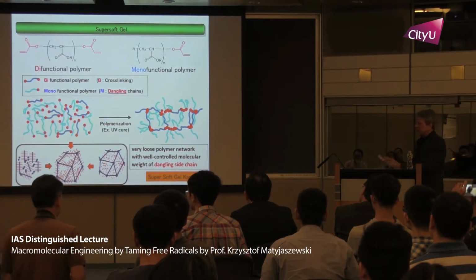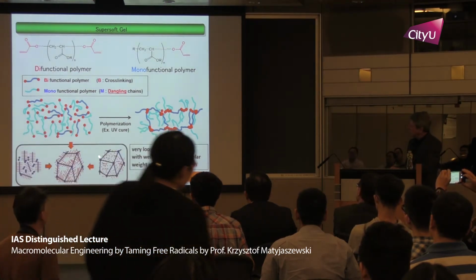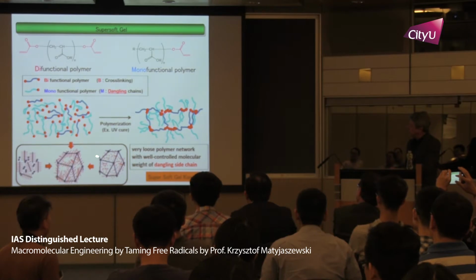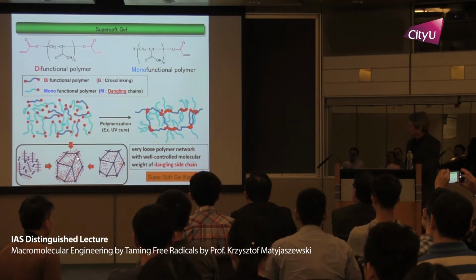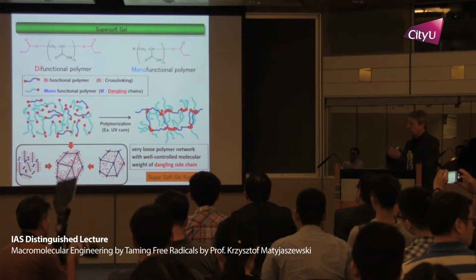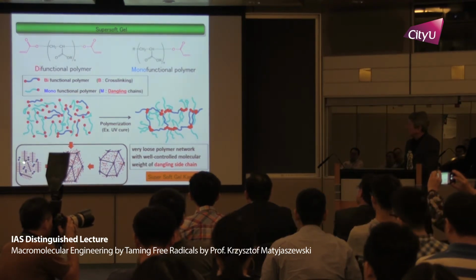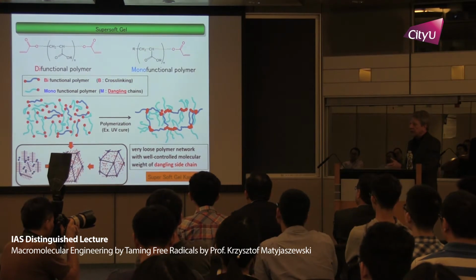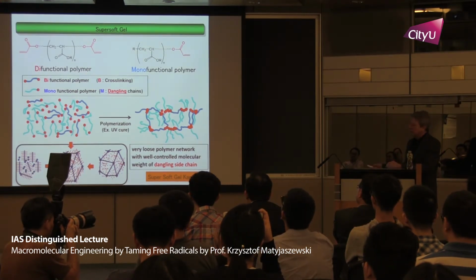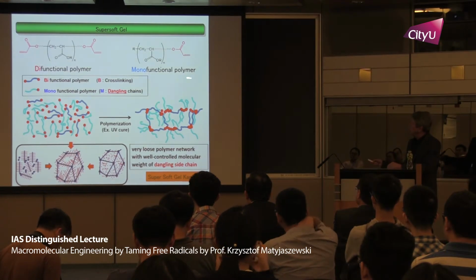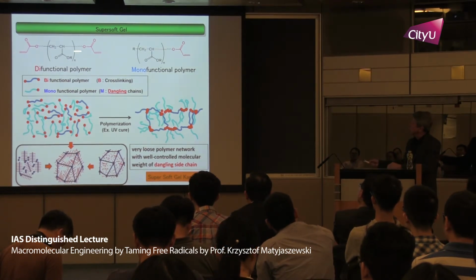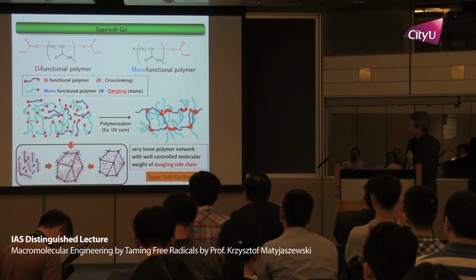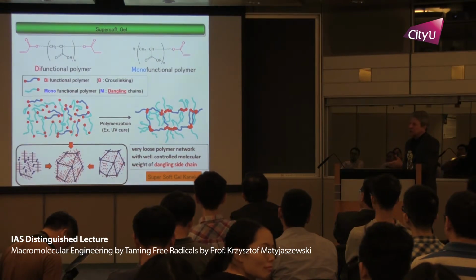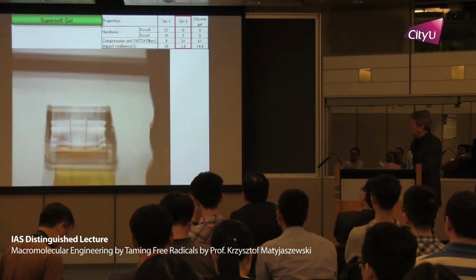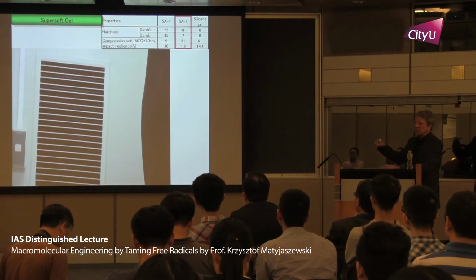You can make them, as I mentioned to you, in two ways. One is that I start with a network, dissolve it not in water, but in monomer, and grow side chains. Not too long, because they will start entangling. So I start with the brushes and connect them together. But in fact, at Kaneka Corporation in Japan, they use an even simpler approach. They make monofunctional and difunctional crosslinkers. And in that case, you use a very large amount of diluent and a small amount of crosslinker to get, roughly speaking, a similar material.